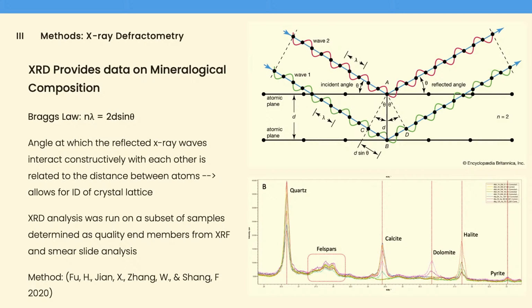The next method of analysis that I used was X-ray diffractometry to collect mineralogical composition data. Similar to XRF, X-ray diffractometry also uses X-rays to perform its analysis. If you focus on the upper diagram there, we have an incident X-ray coming in to a crystal lattice structure. So we have the atomic planes there. Those are those black lines with the dots on them indicating the single atoms. If you can imagine that as like a 3-dimensional crystal. The incident X-rays are bouncing off of the crystal planes and being reflected at an angle. And at just the right angle, the peaks and troughs of the reflected waves line up with each other, and that is constructive interference and results in a rapid increase in intensity that we can identify.